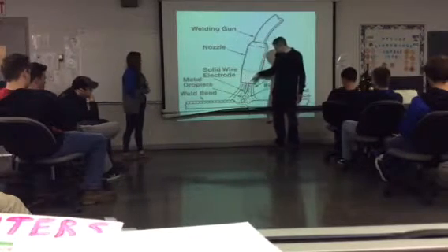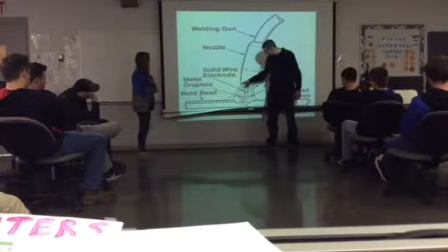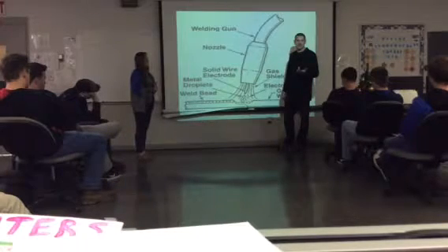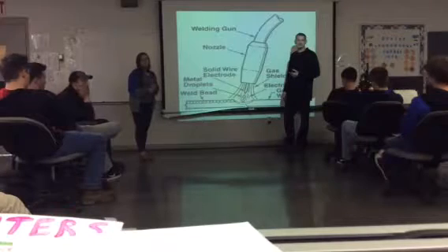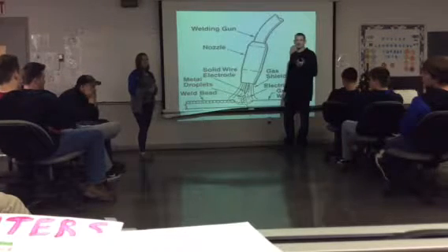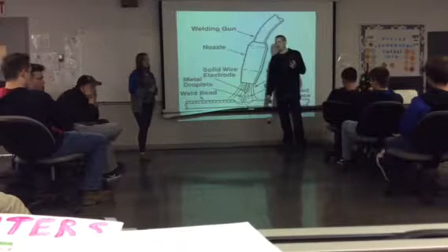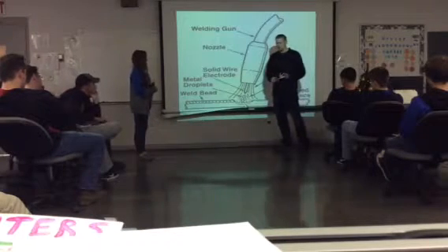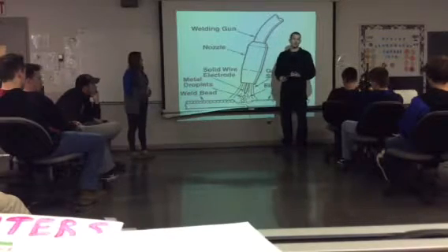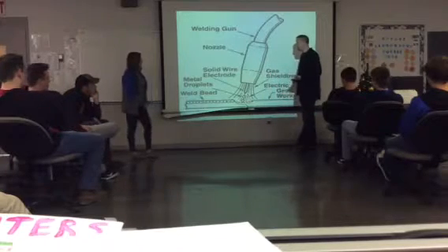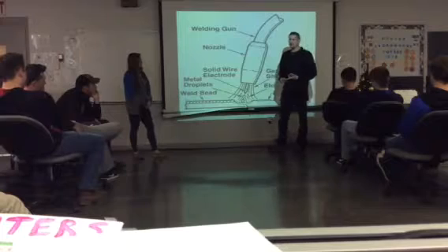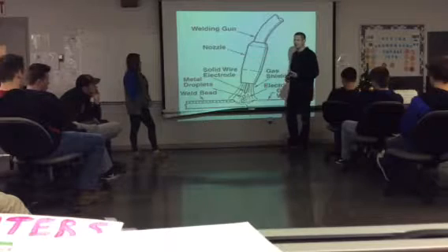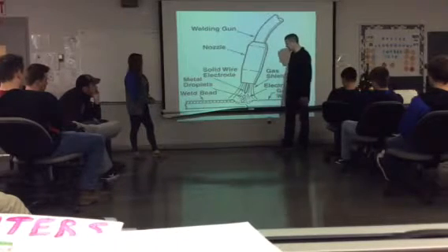Just the same as I showed you on the stick welding a minute ago, what have we got going on right here? Gas shield. That's the shielding gas. What are they? Argon or, helium, what's one, Haley? Carbon dioxide. One more. Oxygen. The gas we use in the shop mostly is 75% argon, 25% carbon dioxide. If we're doing aluminum, it's always 100% argon. I often don't tell you this enough. I don't go into enough detail telling you guys this, because a lot of times I just do it.